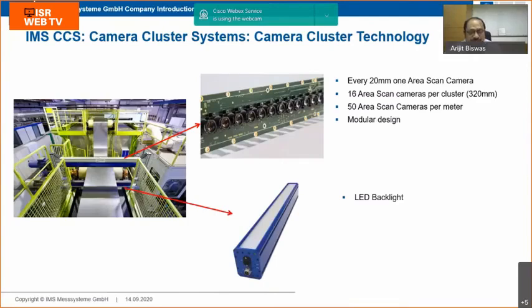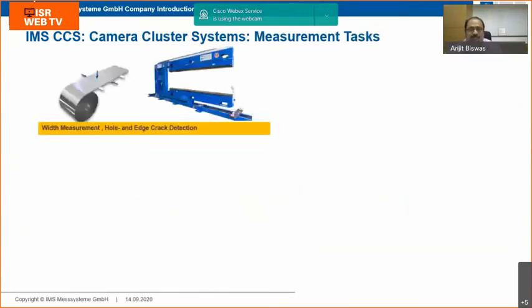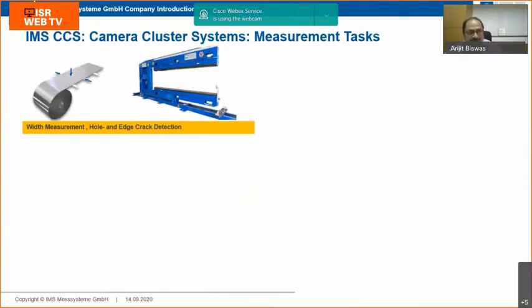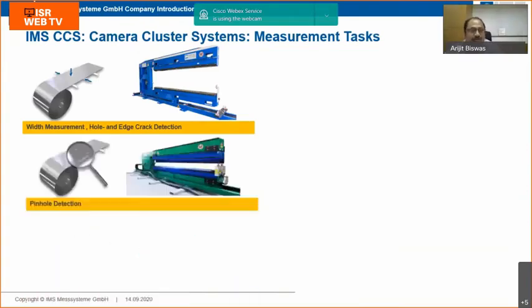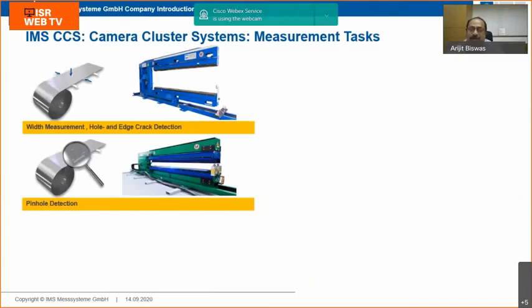Then we are using an LED backlight, because for the cold mill we need light to illuminate the strip. This camera cluster technology system is as of today only applicable for cold mill applications. These are the measuring tasks which can be done with one system. This same camera cluster system can also be put into the C-frame, and we are able to measure the width, hole, and edge crack with one single system.